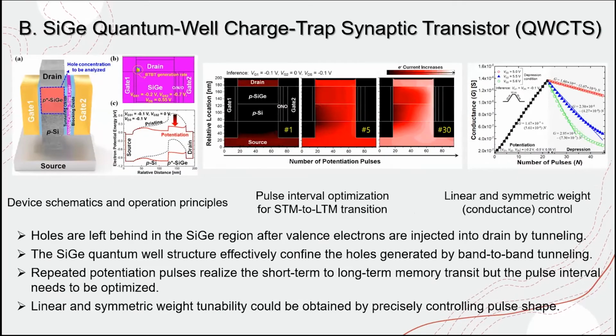In the silicon germanium quantum-well charge trap synaptic transistor, which is also evolved from the 1T DRAM with the quantum well structure, if you look at the right side of the structure, you can see the silicon nitride layer for charge storage. So this synaptic transistor is a combination of quantum-well 1T DRAM and charge trap flash memory together. After a certain number of pulses, the short-term memory transits to long-term memory. The rightmost figure shows the linear weight tunability depending on the number of pulses, for potentiation and depression in the same graph. The figure shows a high degree of linearity and good symmetry about the point discriminating the potentiation and depression process.